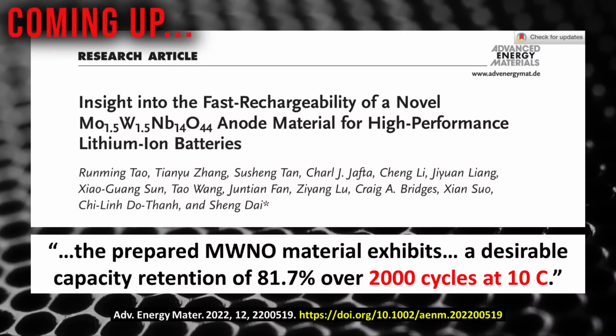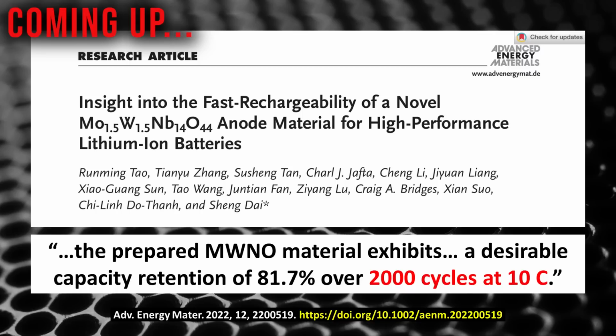It looked like at the very end of the research paper, you mentioned a charging rate of 10C. Is that what I saw there? You were able to charge at a charging rate of 10C, which I understand to be a 6-minute fast charge, full charge, 6 minutes. And you're able to achieve 81% capacity retention at 2,000 cycles, charging at 10C. Is that what I'm understanding correctly? Yes, you are absolutely correct. Yes.